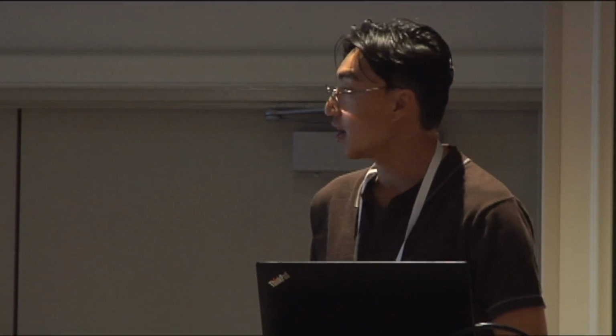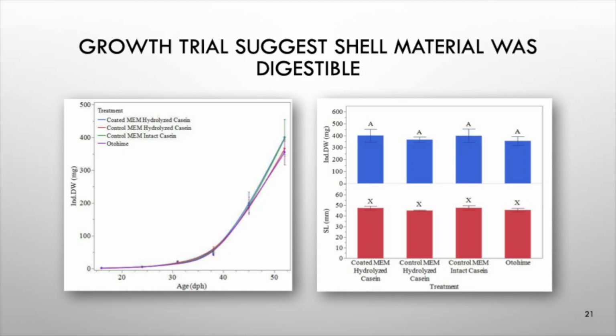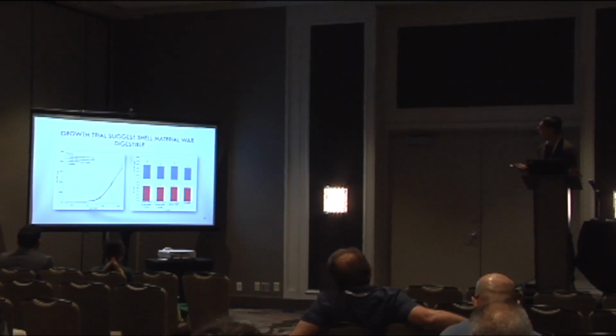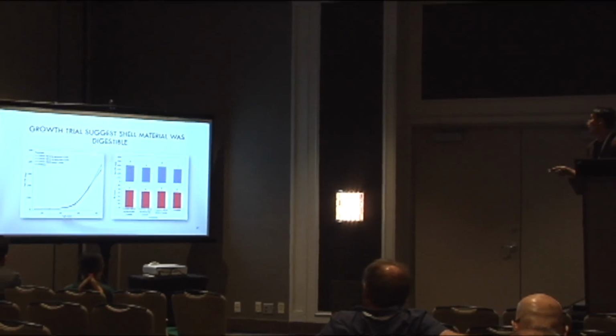All right, so for the results of the growth study, we found that the coated diets performed slightly better than the other treatments, albeit not statistically significant. In the graph on the left, you can see age, days post-hatch on the x-axis, and individual dry weight on the y. And as you can see, the coated MEM, which is the green, and the uncoated intact casein performed the best, but they were, again, not statistically significant.